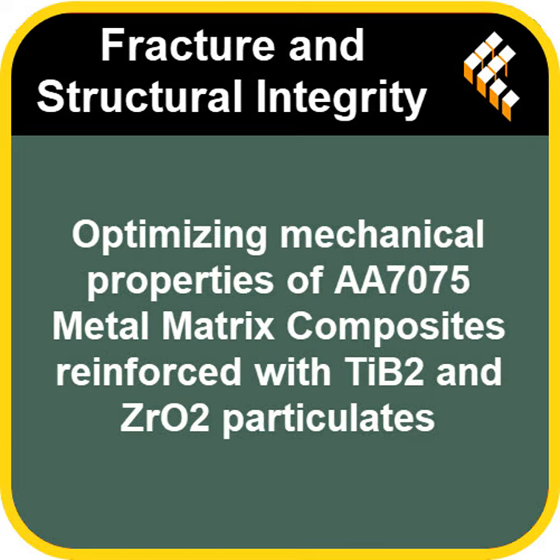Interesting. Anything else from the elemental analysis? One more thing. They detected traces of iron. Iron. Where did that come from? The aluminum composite doesn't have iron. Right, but the counter surface they were rubbing against in the wear test was a steel disc. Steel is mostly iron. So some of the steel disc wore off onto the sample. Exactly. It suggests the formation of what's called a mechanically mixed layer, or MML. Tiny bits of material from both surfaces get transferred and mixed together right at the interface due to the intense rubbing action. This MML can also influence the friction and wear behavior.